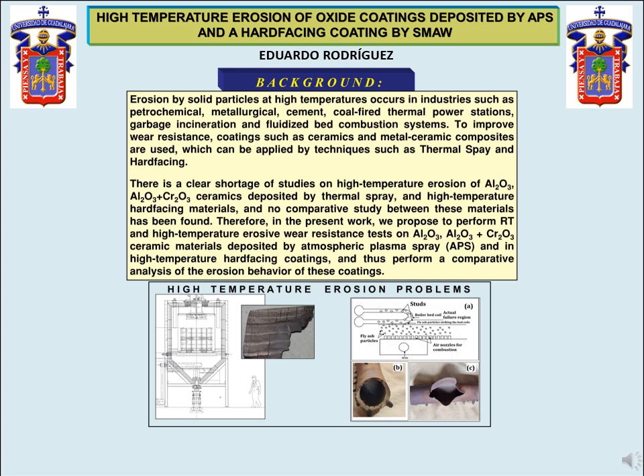There is a clear shortage of studies on high-temperature erosion of alumina, the combination of alumina plus chromium oxide ceramic deposited by thermal spray, and high-temperature hard-facing materials, and no comparative study between these materials has been found. Therefore, in the present work, we propose to perform room temperature and high-temperature erosive wear resistance tests on alumina plus chromium oxide ceramic materials deposited by atmospheric plasma spray and on high-temperature hard-facing coatings, and thus perform a comparative analysis of the erosion behavior of these coatings.